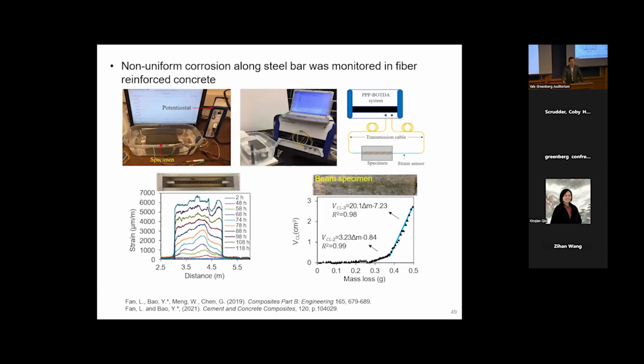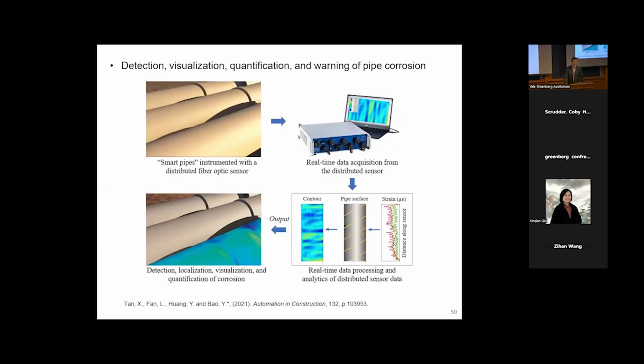And then we apply this to monitor fiber reinforced concrete. We put this in salt, let it corrode, and then we monitor the strain distributions. Then based on the strain distributions, we have a mechanical model to quantify the mass loss because of corrosion. So basically, we were able to not only detect whether corrosion happens, but also locate and quantify the severity of corrosion. So we also received funding for pipelines.